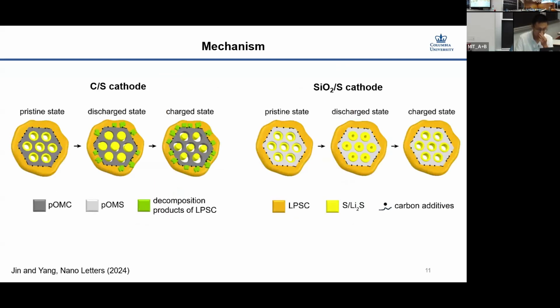So overall, it's surprising that the insulating matrix has better performance, because it does not cause the decomposition of the electrolyte, and so it actually maintains the pathway of ion conduction. And that's why we can get a much better performance than with the carbon matrix.